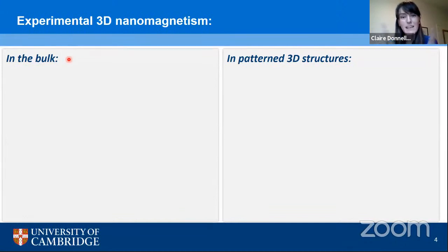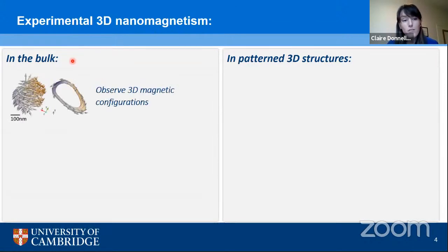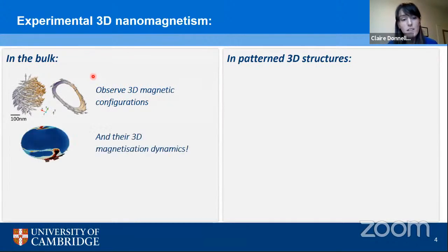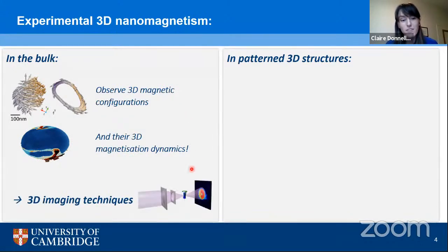Well, by bulk, I mean systems which are large enough that the internal magnetic configuration is not dominated by the shape anisotropy, for example. So this can be structures on the order of hundreds of nanometers, micrometers, or even larger. And in these bulk-like systems where the magnetization is relatively free, we can look for new 3D magnetic configurations with new types of magnetic structures. And of course, look at their dynamical behavior, so how they respond to excitations. And in order to achieve these observations, we need to develop new 3D imaging techniques, which is what we've been doing the last few years.